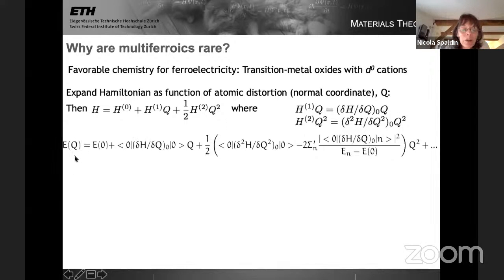And so then the energy in a perturbation theory picture as a function of the distortion is the starting energy plus some first order term. And this first order term is what gives us the so-called first order Jahn-Teller effect. This one's not relevant for ferroelectrics because it's only non-zero for degenerate states and when Q is a symmetric distortion. So that one is not determining whether something's ferroelectric or not. The second set of terms decide whether it's energy lowering for a system to make a ferroelectric distortion.